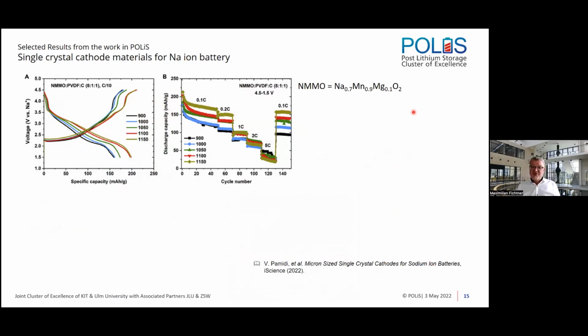Yeah, you see here quite large differences in the capacity of these materials depending on the temperature treatment. And also here are differences at different rates, which get smaller and smaller the higher the rate is. And then eventually at pretty high rates, 5C, the whole thing turns around. And this is where we think the fact that you have a large crystal and long diffusion distances takes its toll.